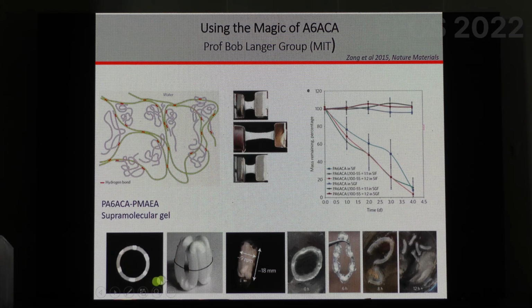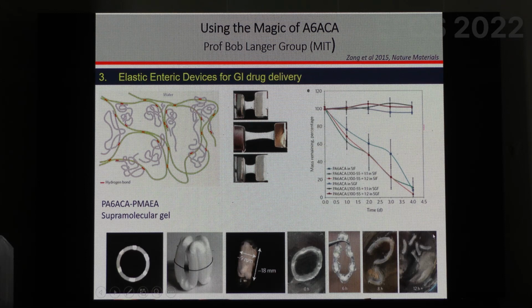This is actually a ring of this polymer joined together by other polymers that can dissolve in presence of low pH. And so you have this ring. The ring is loaded with a drug. You can fold this into a small capsule. So this is a capsule, and you can ingest it. And this capsule can go in your stomach, where the gelatin, which is the cover of the capsule, dissolves. And these linkers here, they are also soluble in low pH, which is in our stomach. So they dissolve. So they're starting to dissolve here. So this is the dissolution, and you get these pieces which go then into the intestine.